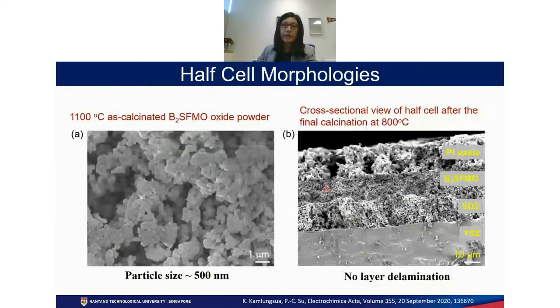So we first look at the powder of the B2SFMO calcinated at 1100 degrees C. The particle size is about 500 nanometers, and you can see that it's rather uniform. And this is a cross-sectional view of the half cell after the final calcination at 800 degrees C. It looks okay, and we didn't see any delamination between the layers, which is a good sign for the integrity of the whole cell.